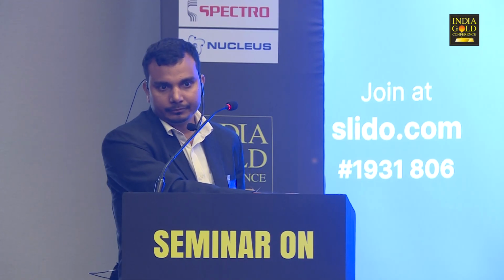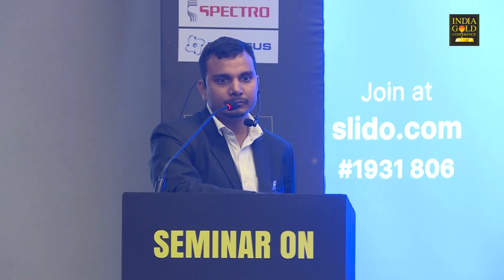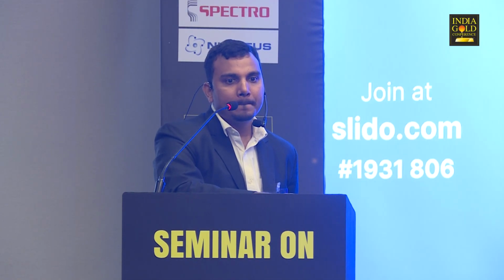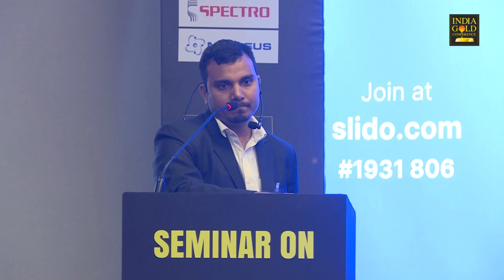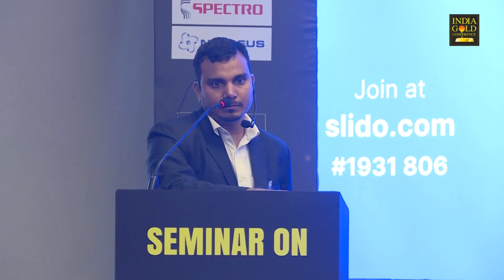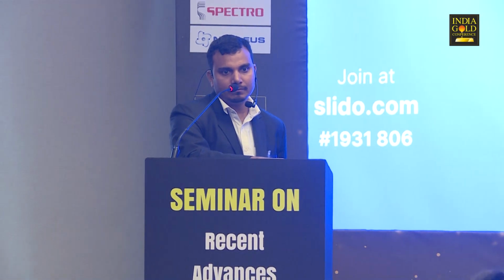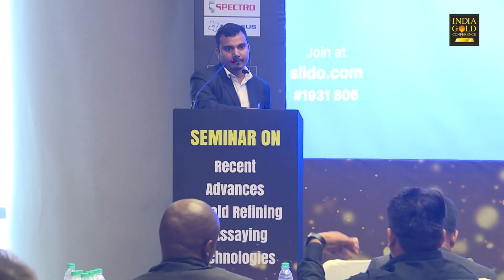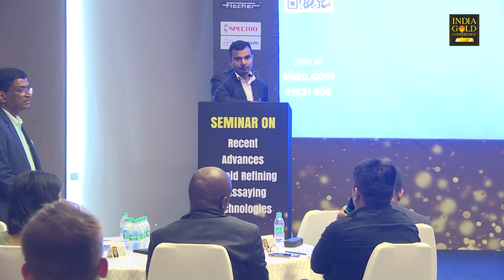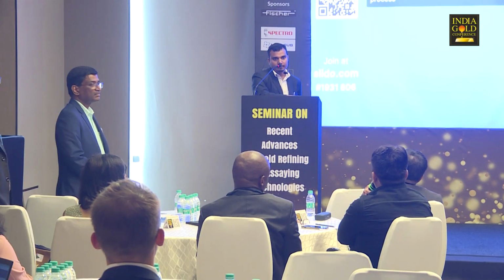Hello sir, I have questions about the sampling and etching of the metal that we are recovering after the melting. What we are facing when we get the metal recovered from the PCB is an issue of inhomogeneity, because there is a lot of tin and iron at the upper surface. So if we remelt it with additional copper, then it is diluting. Then it is very typical to do the analysis and capture it by ICP. And if we are not doing that, then there is inhomogeneity. So how are you sorting out this issue?